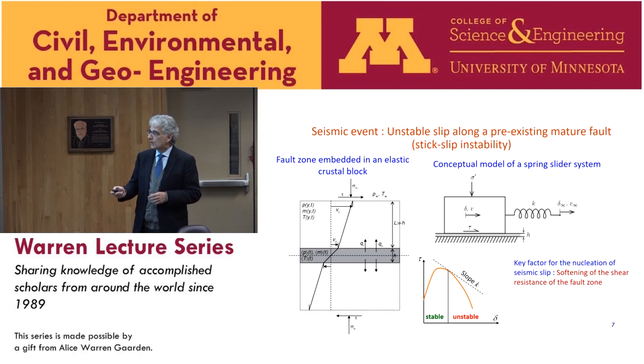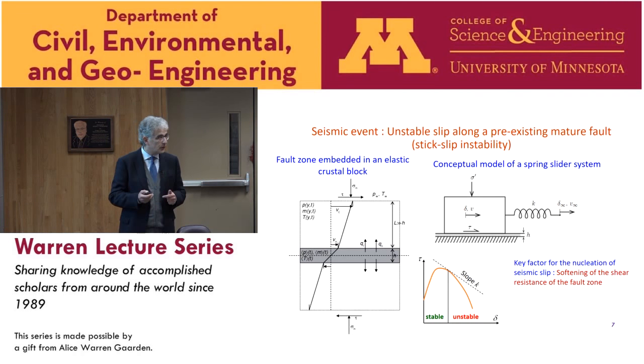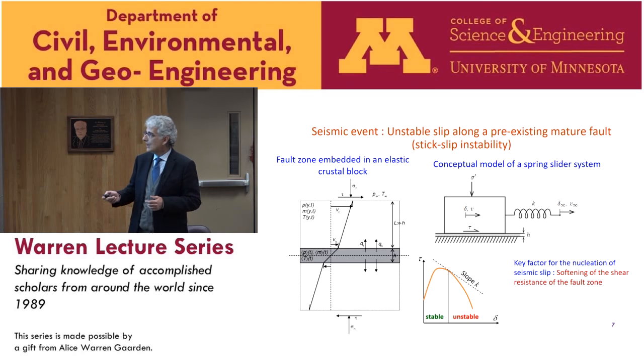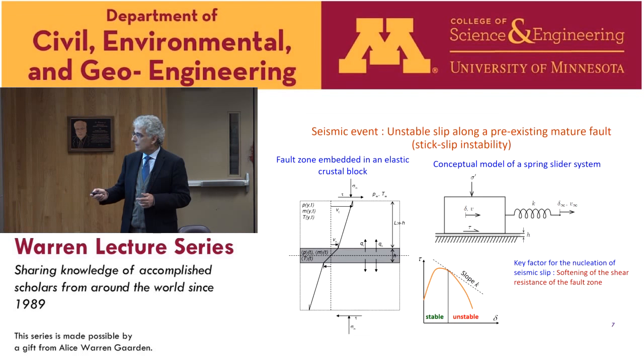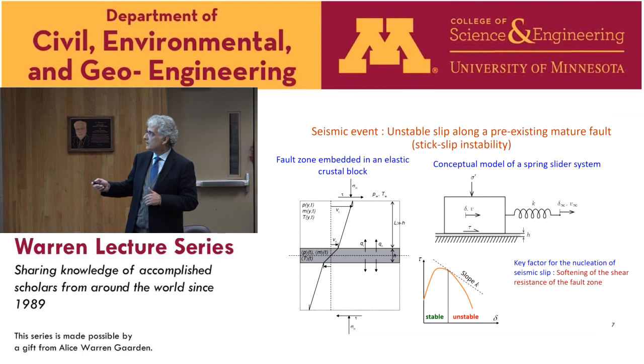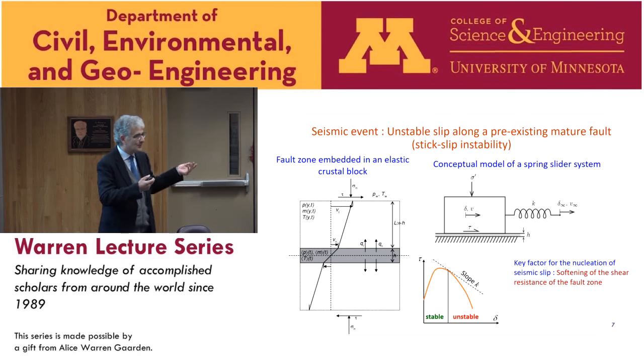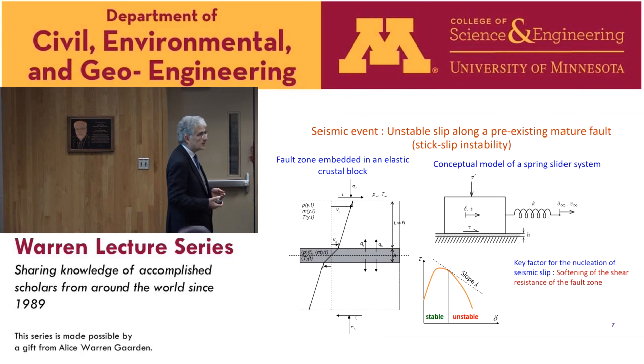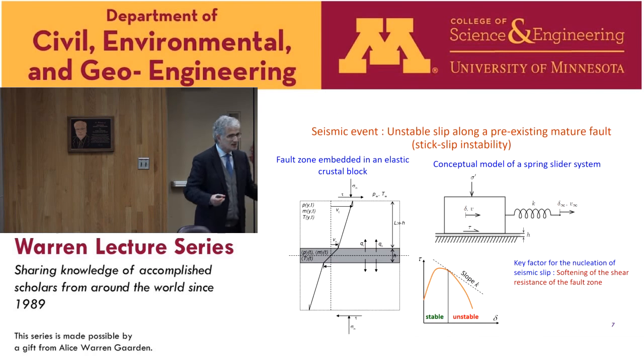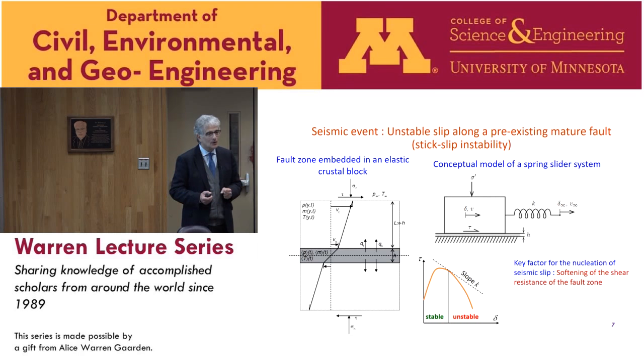This system is used in seismology since Byerlee to understand the stick-slip phenomena and the seismic cycle, because we know that such a system can give rise to instability in the form of stick-slip movements if the rate of the weakening of the frictional resistance at the interface is stronger than the stiffness of the spring. This is also known in other domains, like, for example, in experimental rock mechanics, where we need a very stiff loading frame in order to control the post-peak behavior in a compression experiment.